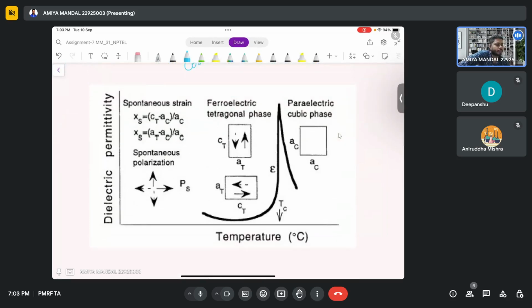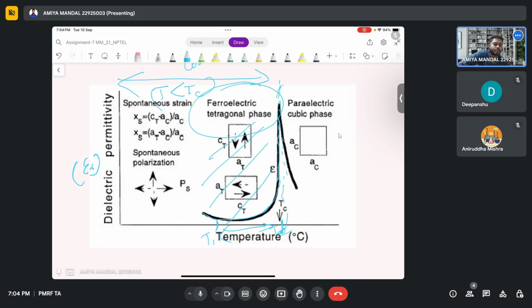So the dielectric permittivity, that is the epsilon R value, how does it change up to Tc? This is the region where T is less than Tc. So I am going from temperature T1 to temperature Tc, and in this region the dielectric constant is increasing up to Tc. In this region it is showing the ferroelectric tetragonal phase, and in this region the paraelectric tetragonal phase. Sorry, cubic phase. That is the cubic phase, and that is the tetragonal phase, the more stable phase.